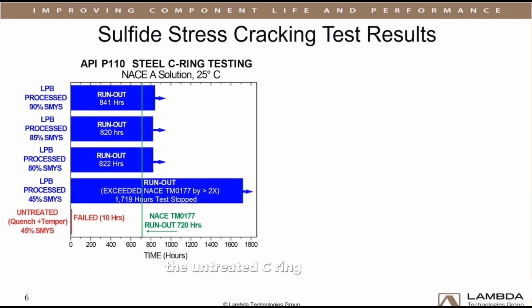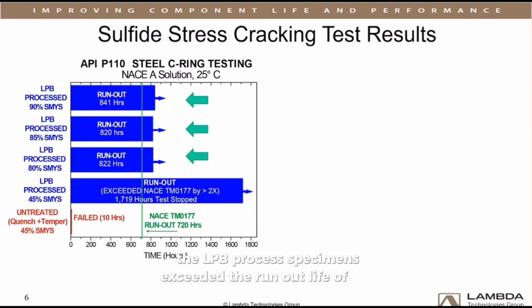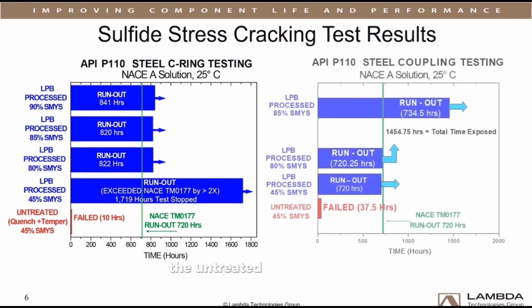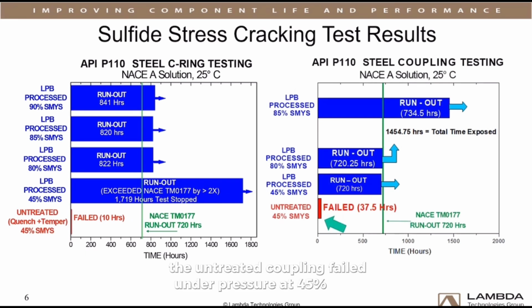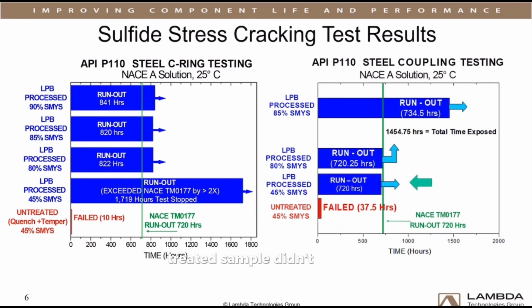The untreated C-ring specimen failed in 10 hours at a stress of 45% SMYS. The LPB processed specimens exceeded the runout life of 720 hours at all loads up to 90% SMYS. The untreated coupling failed under pressure at 45% SMYS after 37.5 hours. The LPB treated sample didn't fail and testing was terminated at 720 hours.